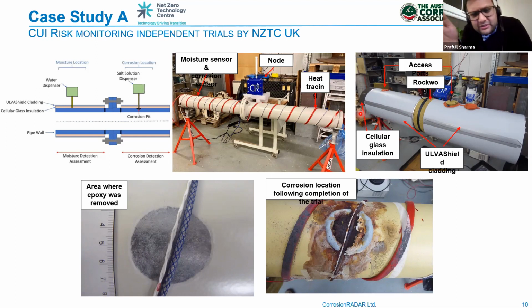Now, when it comes to corrosion sensors, they work and look very similar. For example, in this picture, you can see the corrosion sensor on the right-hand side, within the blue cage, and the white one is the moisture sensor. So they both look like wires, but the corrosion sensor is self-corroding. The outermost layer of the corrosion sensor is made of carbon steel elements. They self-corrode, and it acts like a coupon.